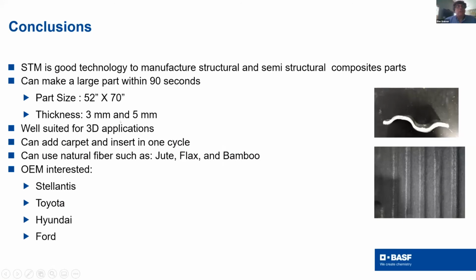As a conclusion, STM, spray transfer molding, is a good technology to manufacture structural and semi-structural composite parts. So eventually we introduced this technology to fit where high pressure RTM has long cycle time. We reduced the cycle time to 60 to 90 seconds, so we're offering that as an alternative. We can make large parts, as I told you. Thickness varies. We were up to 5 millimeters without any problems.